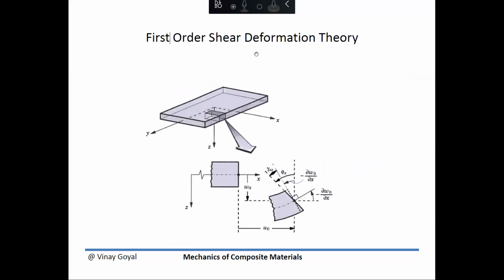In classical plate theory, we had discussed how the normal stays perpendicular to the mid-surface. But in this theory, now you do have a shear term contribution. This transverse shear term was ignored in classical plate theory, and we stated that the transverse shear strain was equal to zero. Recall that gamma xz in this case corresponds to the angle change between the x and z axis. If I have a 90 degree square, that square will stay at 90 degrees as you deform the plate in classical plate theory. But now that angle can be changed. And so we've added that flexibility in this first order shear deformation theory.